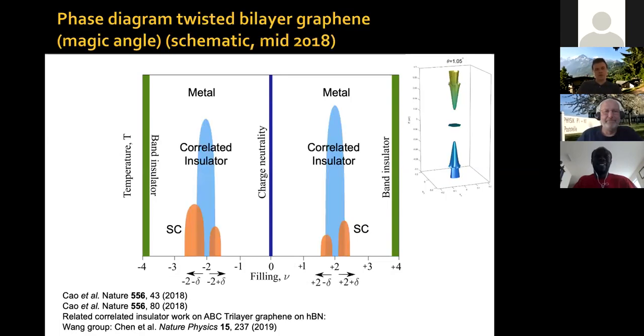Now, if you go to magic angle graphene, this is the phase diagram, and this is sort of schematic as of mid-2018. You have, again, this set of flat bands with large band gaps separating from the other more remote bands. So you have also single particle band insulator states at 4 electrons and 4 holes per Moiré unit cell. You have the charge neutrality point, but at 2 holes per Moiré unit cell, or at 2 electrons per Moiré unit cell, you have a correlated insulator. And when you dope, you have superconducting domes around it.